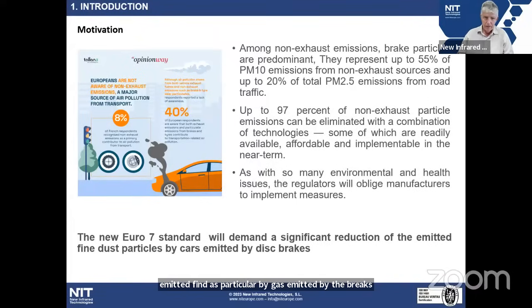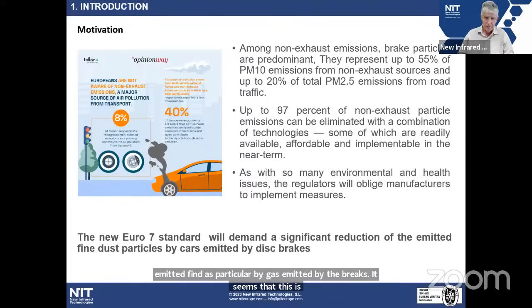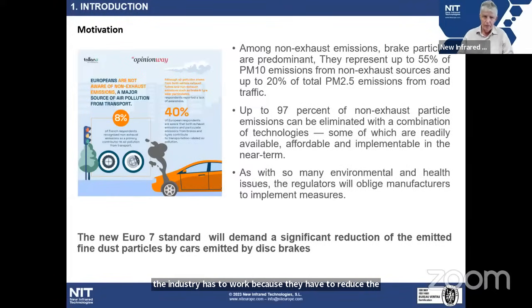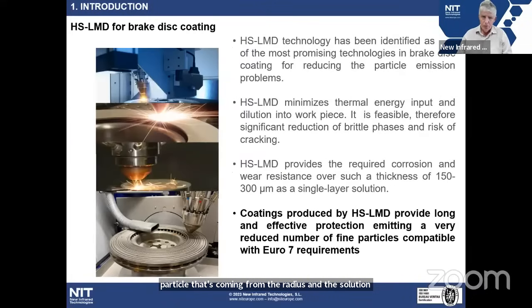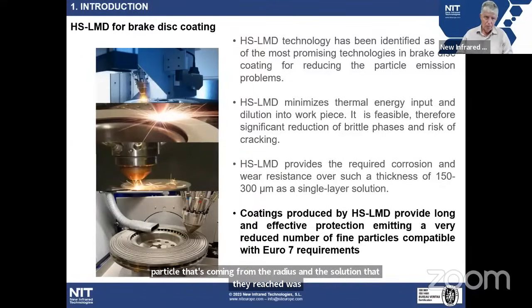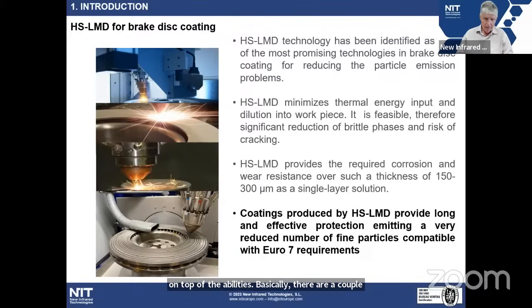The industry has to work to reduce the particles coming from the brake disc, and the solution they reached was to apply a thin layer on top of the brake discs. Basically, there are a couple or three layers, and they looked for the right technique for doing that. Finally, there is consensus in the industry that this coating has to be applied by high-speed LMD, laser metal deposition. The reason is that coatings produced by high-speed LMD provide a long and effective protection, emitting a very reduced number of fine particles, and they are compatible with Euro 7 requirements.